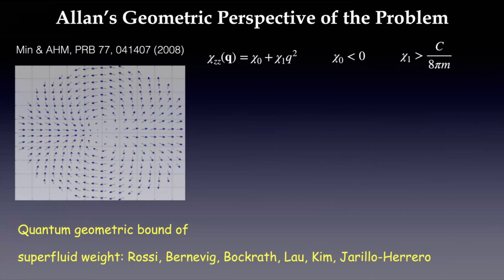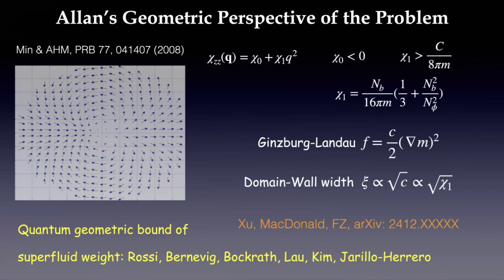That basically says the chiral symmetry breaking ground state is robust to quantum fluctuations. If we fit that into Ginzburg-Landau theory, we'll be able to show the Tc is actually enhanced, and that state is quite stable. That's why people observe this charge neutrality gap phase in many different devices. So we are going to have a paper with Allan. This is also a tradition in his group, to put this in the arXiv paper. It's not my intention to do that. It's just happening this way.